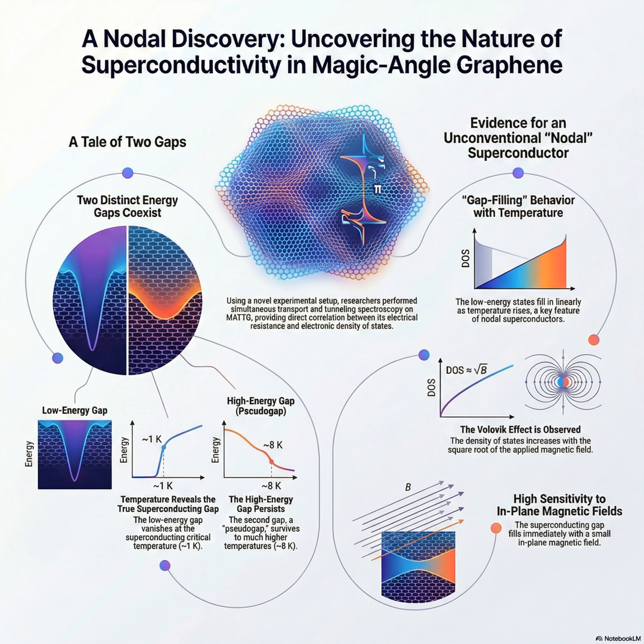Exactly. By confirming the nodal pairing symmetry, MATBG joins this really exclusive club of unconventional superconductors. Which tells us the material is highly sensitive, sure, but its very nature might mean it could operate under different conditions than conventional systems. For sure. And this experimental framework is so versatile. It can now be used to precisely study other sensitive 2D moiré materials, like twisted transition metal dichalcogenides. It gives us the tool we need to start cracking the code on all these correlated quantum phases.